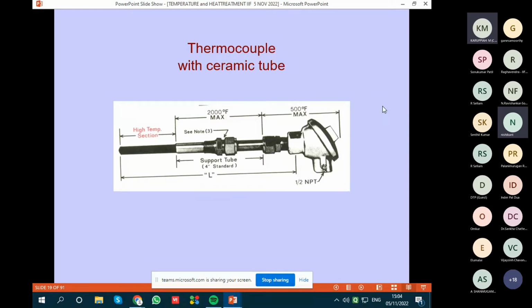The thermocouple head has to be outside the furnace and should be as far away as possible from the shell of the heat treatment furnace or any furnace, because if the head gets too hot, then you may get an error. But generally, the head is designed in such a way that it is quite far from the thermocouple length, and this problem should not arise. But just ensure, in case your head is very close to the furnace, try to increase the length of the thermocouple and bring it a little away from the shell.